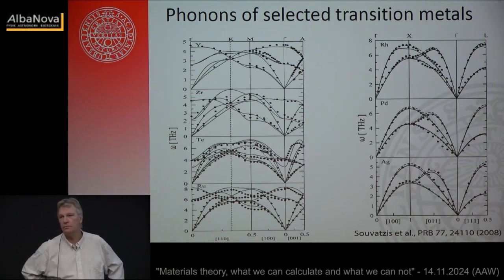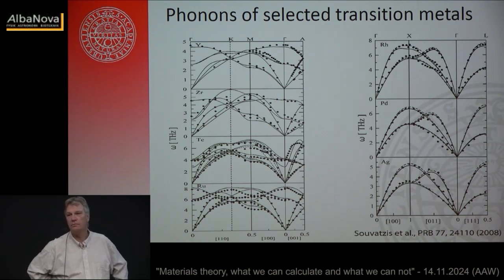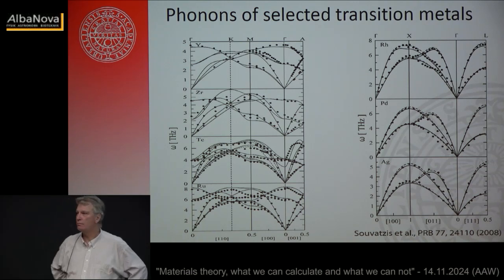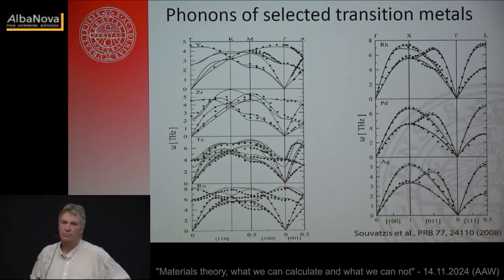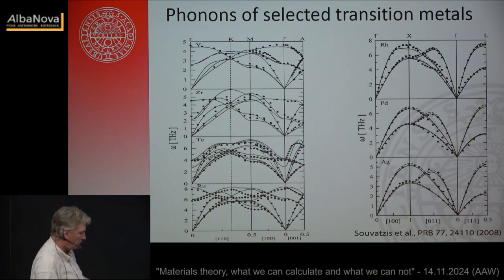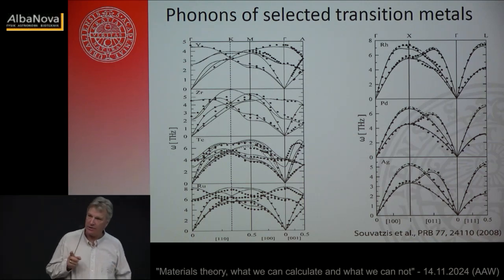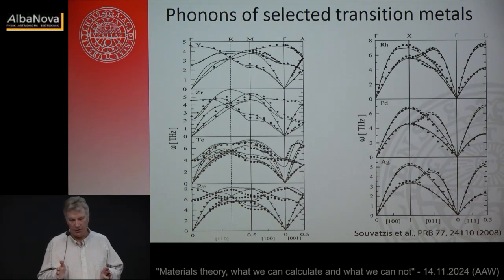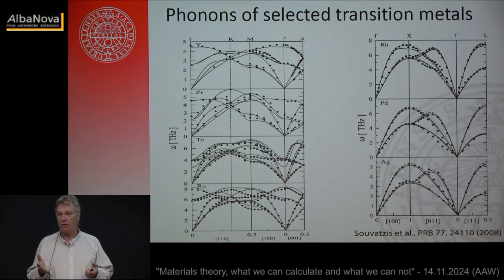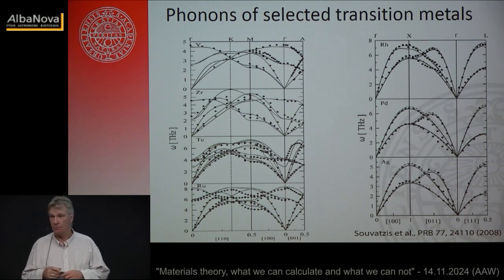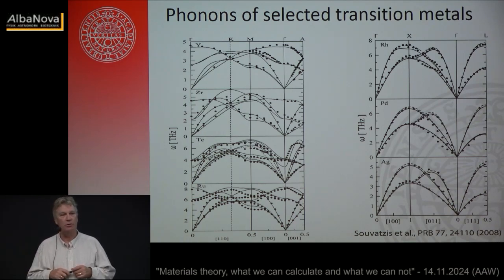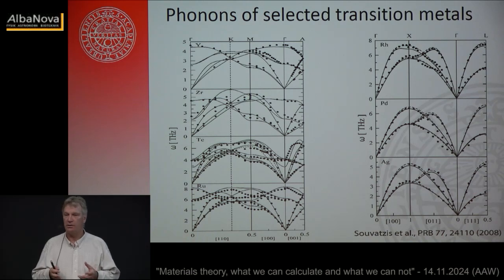I guess why DFT fails in the phase diagram is because the energy differences are very small between the different phases. Can you put a number on that? Like how accurate is DFT in energies? What's the typical failure for energy? In some ways, when you calculate elastic constants, something we also amused ourselves with doing, you have to be on a micro Rydberg level. So that's very delicate, and there we were okay, and other people also. But then it was a change. If I distort something, I change something, that's okay.